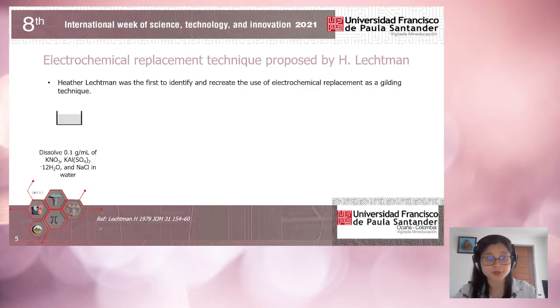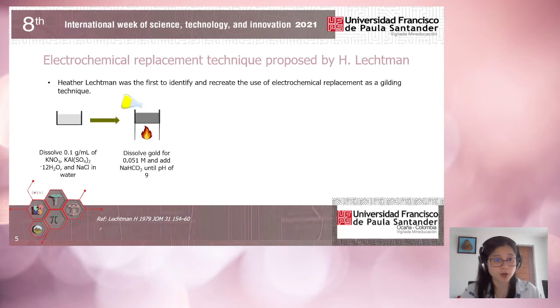Heather Lechtman was the first to identify and recreate the use of electrochemical replacement as a gilding technique. She described very well a protocol that I'm going to present right now. She used 3 salts. These 3 salts were known by ancient citizens in this part of Peru. She used a 1:1:1 mass ratio with a concentration of 0.1 grams per milliliter. These salts were potassium nitrate, potassium aluminum sulfate, and sodium chloride. She dissolved them in water.